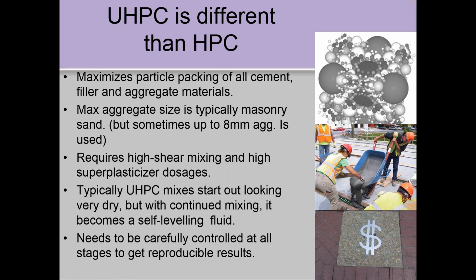It's very dry to begin with because you're looking at water cement ratios less than 0.2. And so it looks like dry sand almost. And you mix it and mix it and mix it, and eventually after a period of time it starts to flow and it becomes this liquid material like that wheelbarrow there showing in the picture. And it's typically self-leveling, but to get reproducible results, there's a lot of control that has to be exercised. And of course, it's expensive. It's in a whole other ballpark for cost.